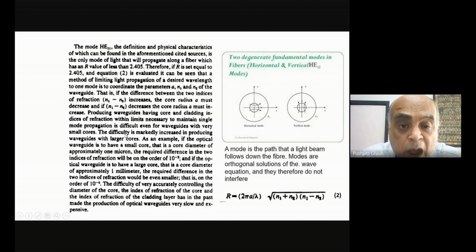The difficulty is markedly increased in producing waveguides with larger cores, because if the core is larger, just like you need for multi-mode transmission, then the difference between N1 minus N2 must be extremely small. As an example, if the optical waveguide is to have a small core, that is a core diameter of approximately 1 micron, the required difference in the two indices of refraction will be of the order of 10 to the power minus 2 in the second decimal place.